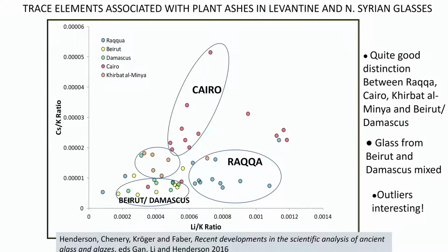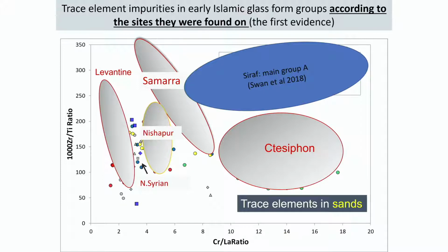Okay, so if we then look at other elemental ratios in sands, chromium, lanthanum, zirconium, titanium, we can actually see that we have some nice concentrations of data according to the sites on which they are found. Ctesiphon, Samarra, and Siraf, Nishapur up to a point, and very distinct from the Levantine glasses, with northern Syrian glasses being squeezed in between. That's not been identified or found for any other period of the study of ancient glass that I'm aware of. And the fact that Ctesiphon and Samarra are really quite close geographically was a surprise to us, I have to say.